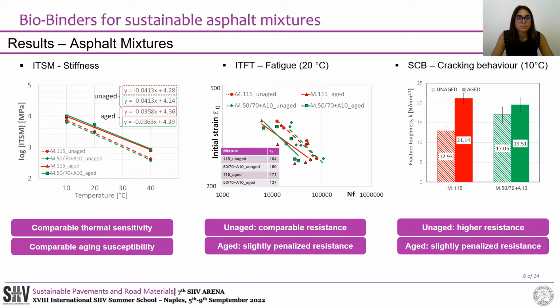From the ITSM test, the bio-oil-based asphalt mixture shows perfectly comparable stiffness properties with the reference one, denoting a comparable thermal and aging susceptibility. As far as fatigue resistance is considered, no substantial differences emerge in unaged conditions. Differently, a slightly reduced performance is attributable to long-term aging, which shows a higher slope of the fatigue envelope and a reduced epsilon 6 value.